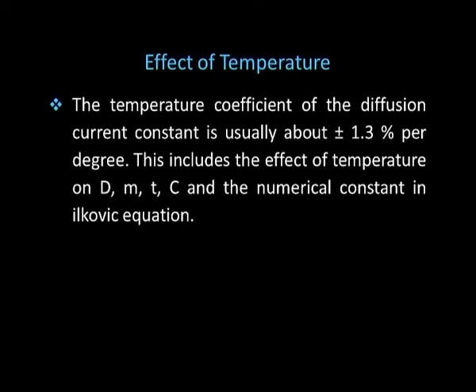If we carry out an experiment at different heights of mercury reservoir and plot the current against under root h, we will get a straight line proving that the current is diffusion controlled. Then effect of temperature. The temperature coefficient of the diffusion current constant is usually about plus minus 1.3% per degree, which includes the effect of temperature on density, mass, drop time, concentration and the numerical constant in Ilkovic equation.